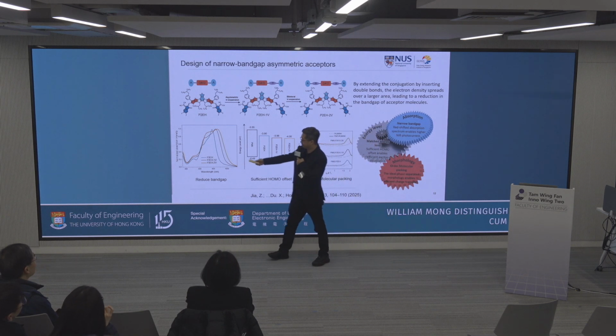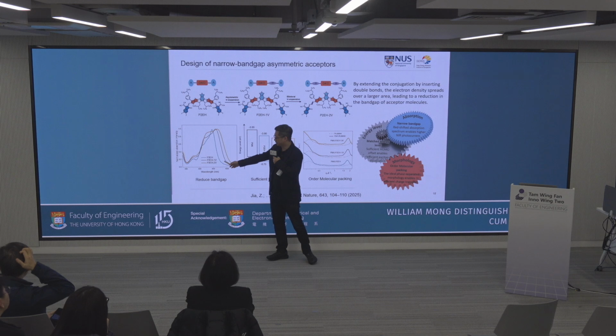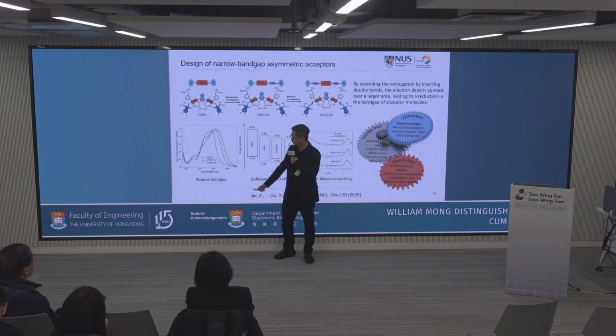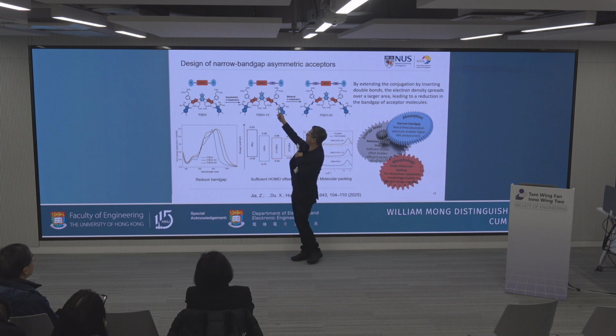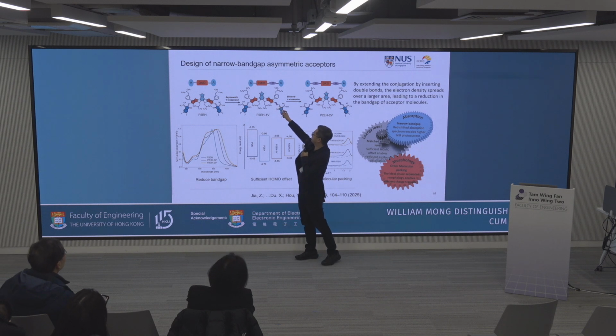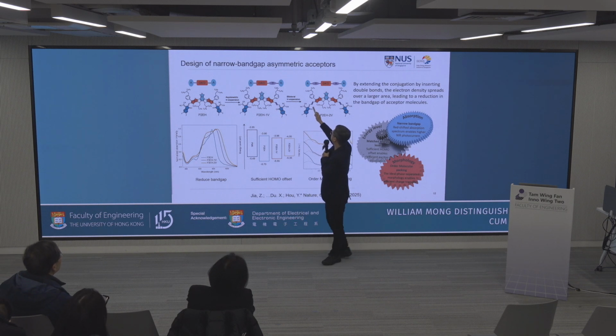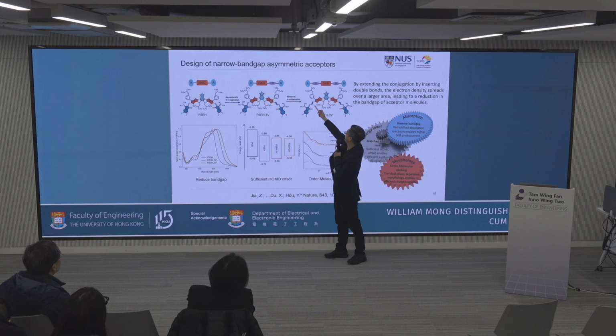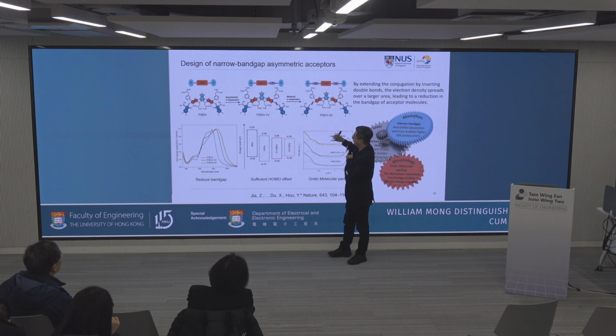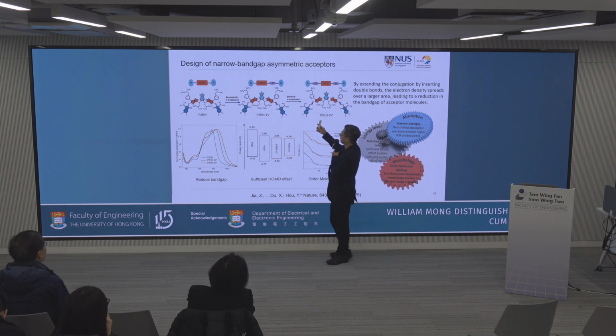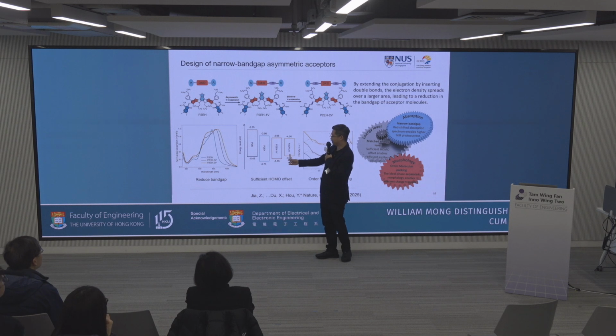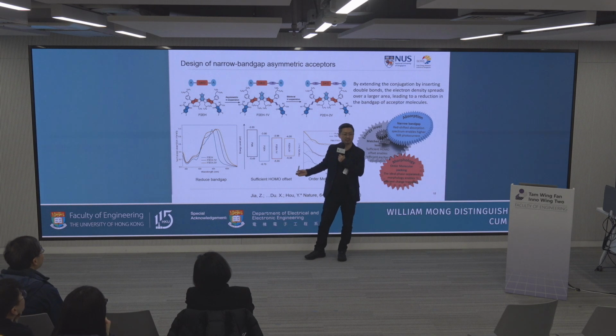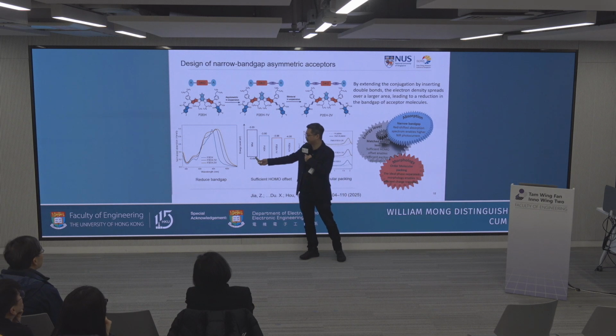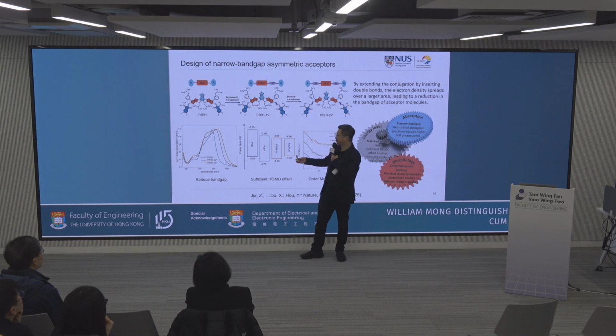So this is the control. If you look at this one, the band gap, as I said, is about 1.35. And what we did is, we made some innovations with this double bond. We introduced this double bond to this part. There are actually two opportunities to introduce a double bond. One is here and one is here, and both can narrow the band gap. But this narrows it too much. We upshift this HOMO level too much, so we don't have a driving force to dissociate these excitons. The hole cannot transfer to here. Then we don't have a good performance device.